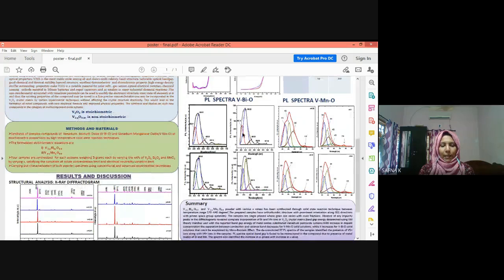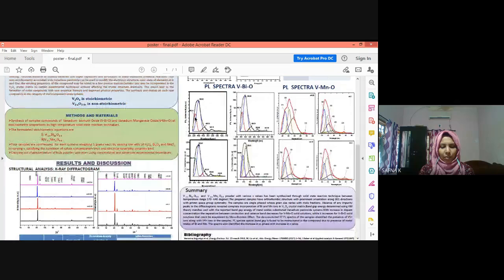And this represents the PL spectra of the prepared samples at room temperature. Major emissions were observed around 370, 400, 460, and 535 nanometers. The emissions have been mostly attributed to radiative transitions between electron-hole combinations. The emission at 370 nanometers is due to valence uncertainties of vanadium, and the one at 400 nanometers indicates the excess presence of V4+ ions along with V5+ ions in the crystal.